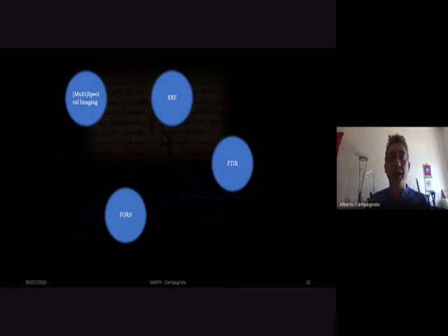Multispectral imaging only gets us as far as identifying generic materials. If we want to get more details, we have to go into different kinds of spectral analysis like XRF, FTIR, and so on. But all these normally act on a very specific and very tiny area. So multispectral imaging allows us to first get a mapping of all the different materials that we have on the object. And then we can say, oh, I need to understand better what happened here. And you can do XRF on one very specific dot, or get different kinds of analysis done on very specific areas of interest.